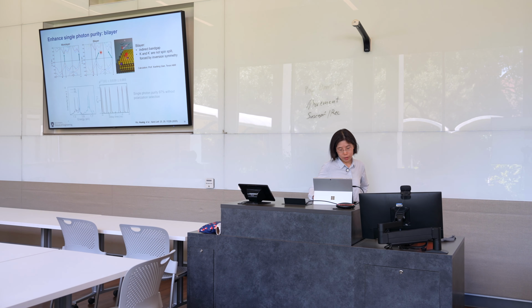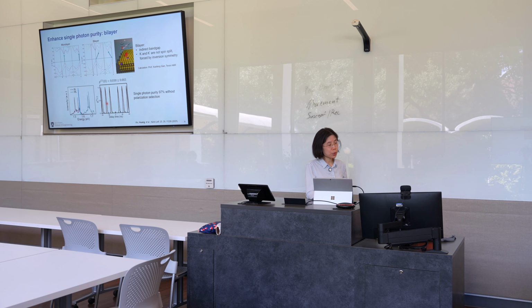So let's look at our experimental results. So this is a bilayer PL or photoluminescence spectrum. You can see the single photon emission. Here, the intensity is not compromised compared to monolayer, and the background is also suppressed. And as a result, we can have a G2 of 0.03, which corresponds to a high single photon purity of 97%.